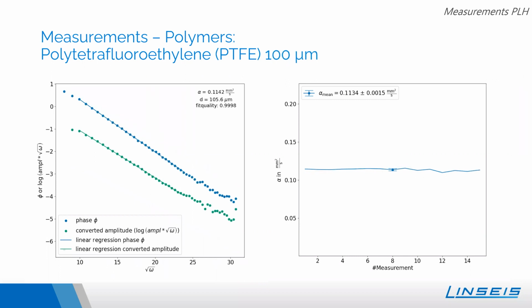And if you double the thickness of the sample, the thermal diffusivity of Teflon hasn't changed. It's still around 0.11 millimeters squared per second. And as you can see, our measurement still matches this value. If you repeat the measurement, it's still very precise, and the value is in the range of the measured thermal diffusivity.